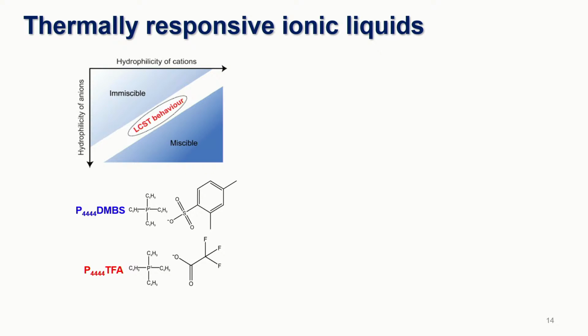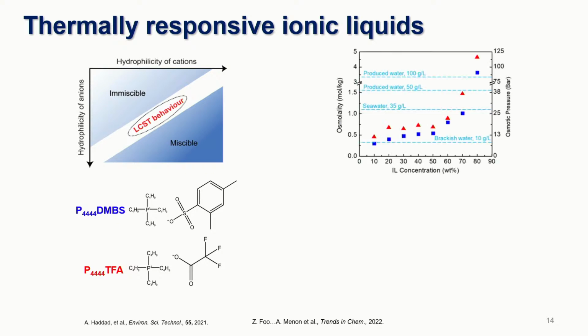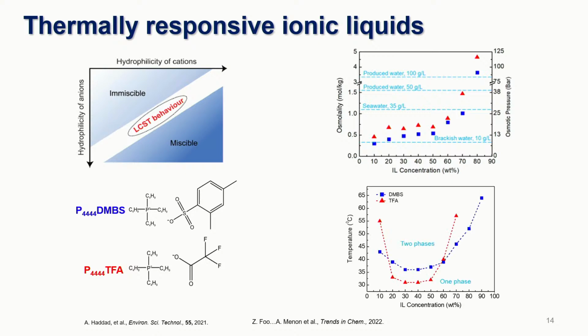So some of the ionic liquids we work with, again, just organic salts, right? It's a phosphonium dimethyl benzene sulfonate and a trifluoroacetate. There's a few different ones that have been reported in the literature to have this LCST behavior. And the properties we care about are the water activity or the osmotic strength of these mixtures, which varies as a function of concentration. And so depending on what kind of water you're trying to treat, you could vary the concentration of your ionic liquid. And then, of course, the phase diagram itself is really important to characterize. And so we just use cloud point measurements with a UV-Vis spectrometer to generate these phase diagrams.